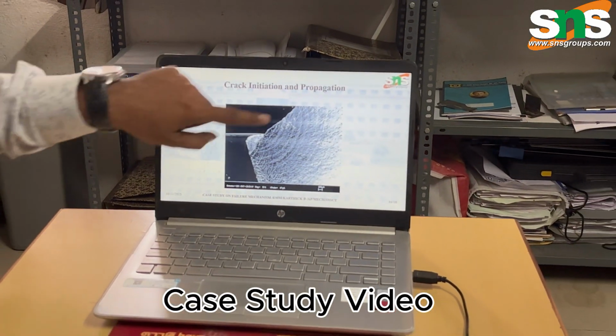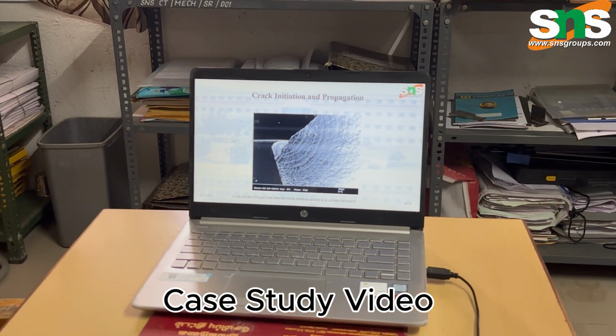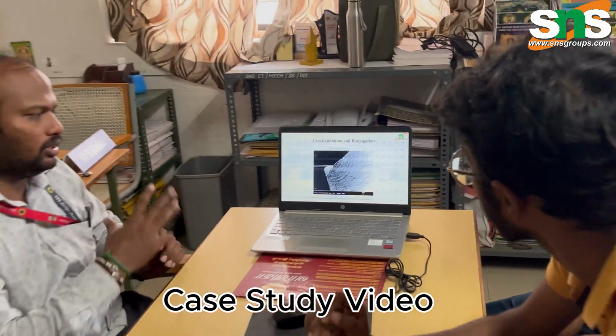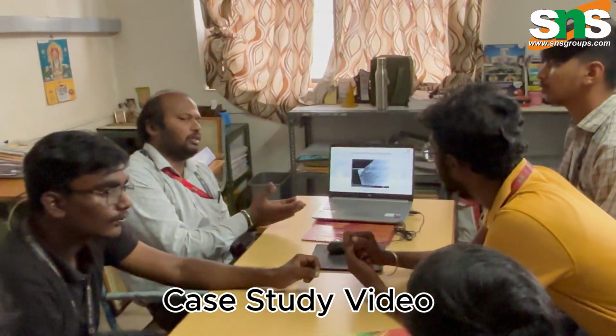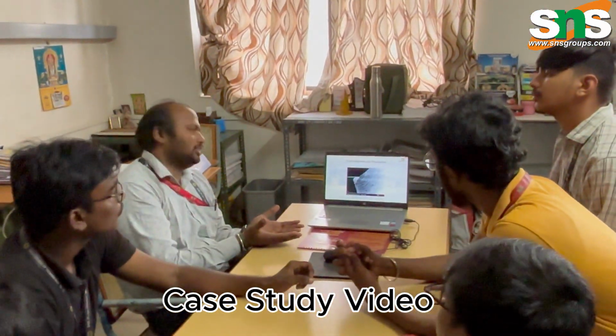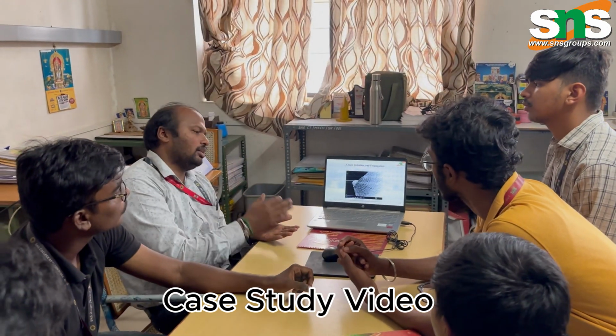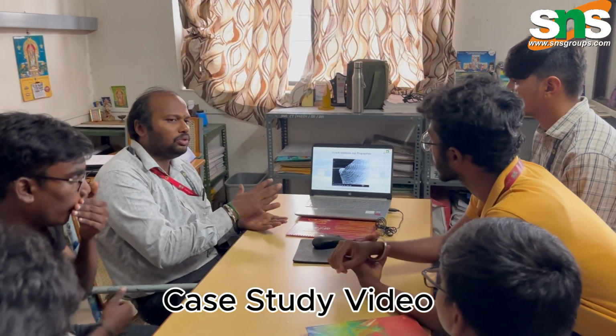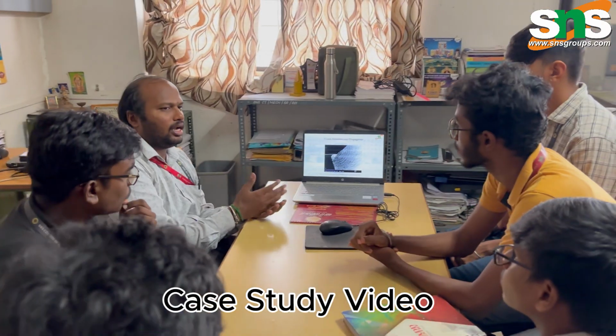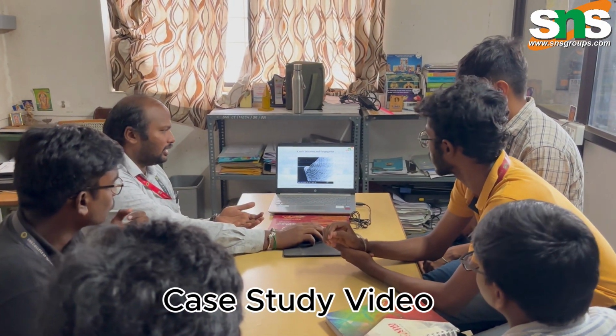These marks are nothing but the fatigue striation marks. With these fatigue striation marks, you can easily find from the same examination that this particular failure occurs majorly due to fatigue, and in addition to that pitting and spalling have taken place.